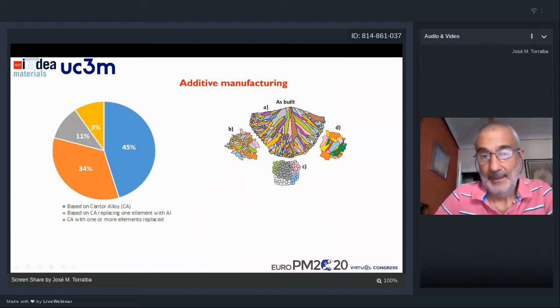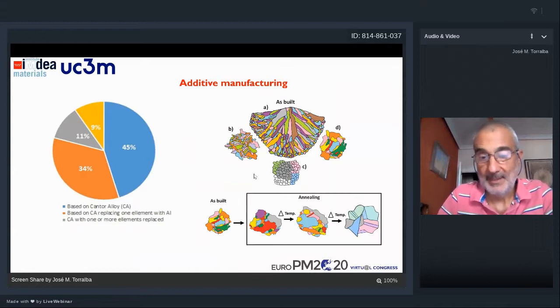In additive manufacturing, in one typical laser bed pool, we can find in the same part different kinds of microstructure: small equiaxial grains in the border. We can have random equiaxial grains, but with different sizes, like you can see here on the left and on the right, and even columnar grains. But usually, after the additive manufacturing process, we can follow with an annealing process in which we can tailor the microstructure and get at the end this kind of equiaxial grains. And in the case of FCC materials, with a lot of clustering